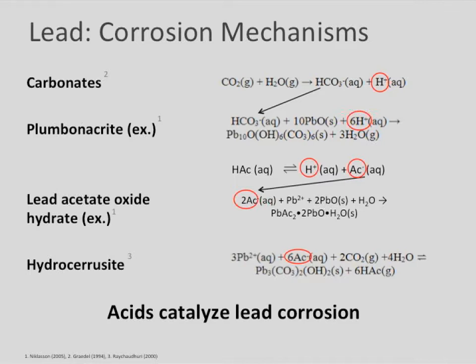And then hydrocerrusite uses that acetate anion in an equilibrium process to form hydrocerrusite. So in all of these cases, an acid is part of the equation and is key to forming a lot of corrosion. Most of the time when you're seeing corrosion on lead coupons, it's because acids are being evolved from your preservation material.